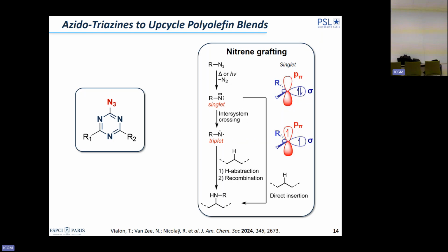And if you think about PE, it's not so bad. You may create a bit of static cross-link because you will create a radical here that can recombine. But if you work at very low concentration of radical, this may be minimal. But with PP, you are going to go on beta scission. So ideally, this is what we would like to do. I would say ideally, of course.